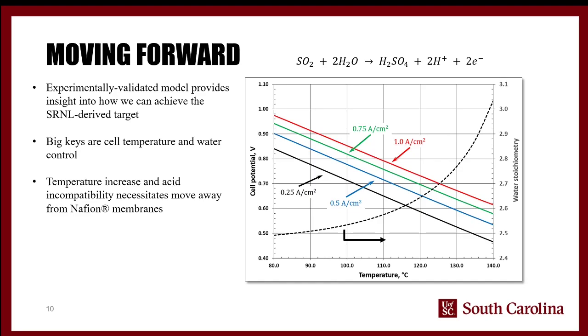That's it. The PBI is incredibly stable. The Benicewicz group did a years-long study of leaching of the sulfuric acid that they actually put into the membrane that gives it its conductivity. And after several years, it had lost less than 5% of the acid that was in there, which is just incredible stability. Similarly, they have no problem with temperature. They actively run it in fuel cells up to 200 degrees Celsius, and it runs for hours, days at a time with no issues. And so that kind of both acid stability and temperature stability is a huge thing, and so that's going to help us moving forward.